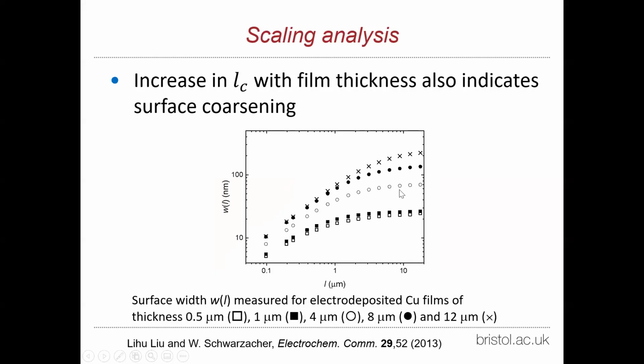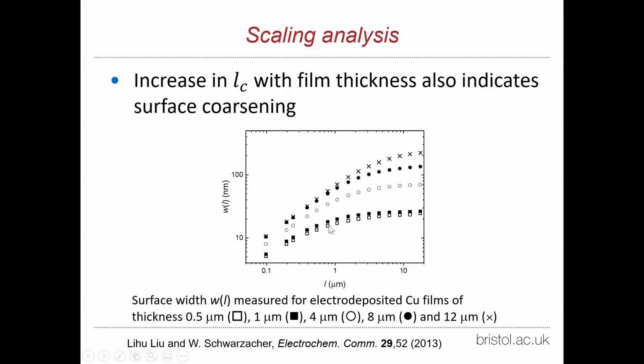Okay, so now I will show you experimental data, and you can see that the shape of this experimental data, this is measured surface roughness, is the same as it would be for the theoretical curve I gave you. You can see here that there is a crossover. Here there is a straight line with constant slope, saturation. And what you can see is that the position of the crossover is moving to here, to here, to here. What that is showing you is that the size of the features is increasing as the film gets thicker.